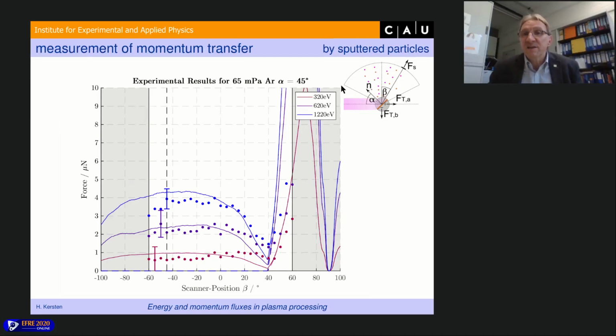And if we are larger than 45 degrees, then we have a very high force. And this is clear. Then we measure the primary ions. Then the primary ions from the beam are going to our probe. But if the angle is lower than 45 degrees, then we do not measure the primary ions, but we measure here the sputtered particles from the target. And this is a quite good agreement. Here it's for different acceleration voltages or beam voltage. In good agreement, the measurements with the simulation.